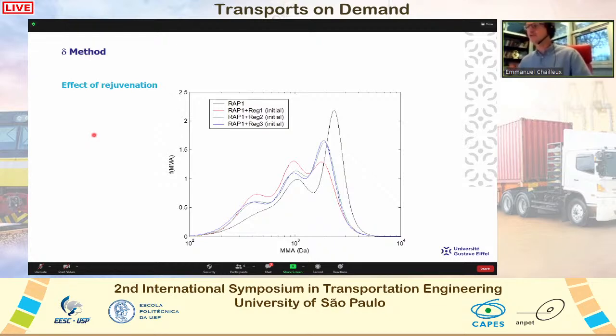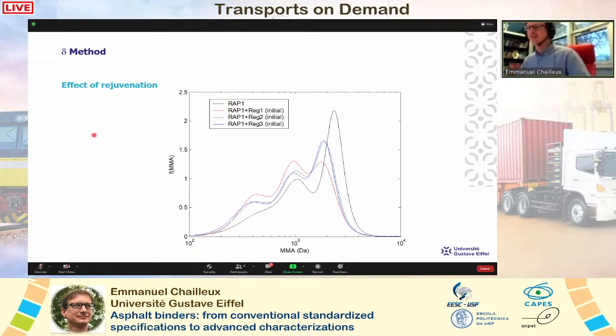So finally, I want to finish with the effect of rejuvenation with the delta method. So in black, you have the distribution of asphalt binder extract from a very old road. So it is a typical distribution calculated from the delta method of a very old bitumen with the population of high mass which dominate the